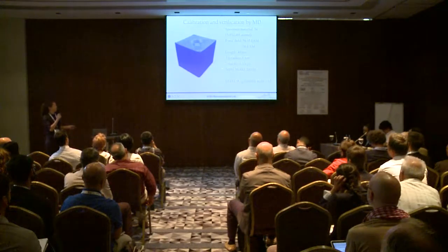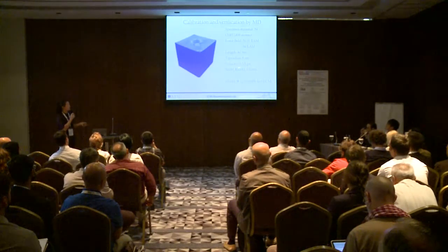The total length scale is a 40 nanometer cube, while the indenter is spherical with a radius of 6 nanometers. The velocity we used is 0.5 angstrom per picosecond. So it's really high speed compared to the experiment. And the hydrogen amount we put in, this is the atomic concentration. So it's the total number of hydrogen atoms that we put in the indentation.